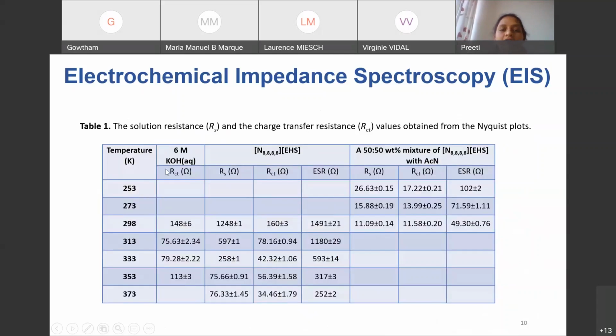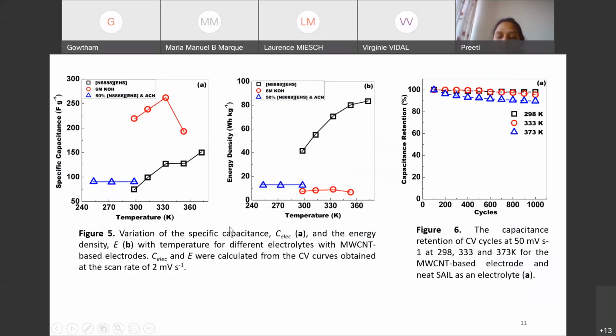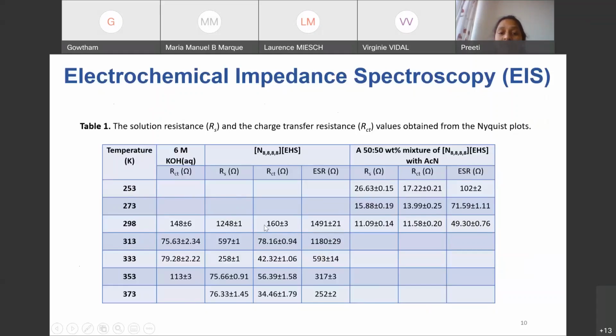So here are the values for better understanding. We have also compared with 6 molar KOH, which is an aqueous solution, the neat ionic liquid, and the binary mixture of ionic liquid with acetonitrile. And what we observed interestingly is, as I told you, that this ionic liquid is highly viscous at room temperature, and the charge transfer resistance and the solution resistance have very high values, 1248 and 160. But when we increase the temperature, the charge transfer resistance becomes even lower than the aqueous electrolyte at room temperature, which is 148, and it is 34.